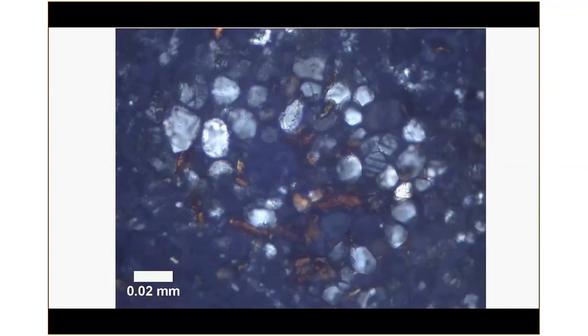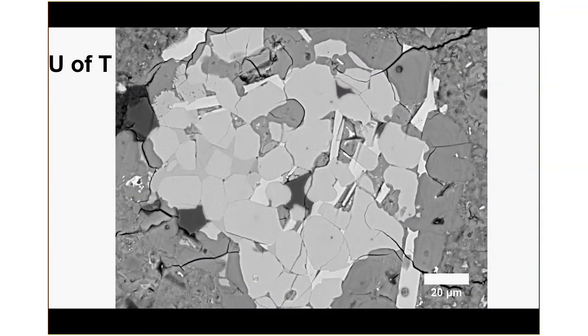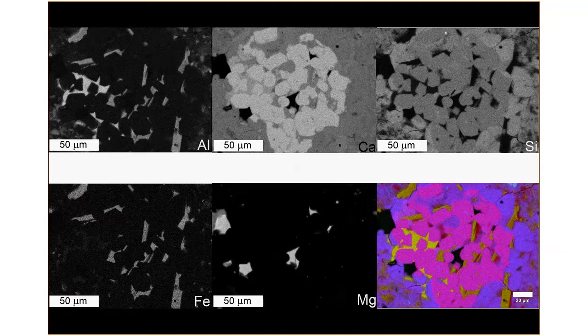Cross-polarized light, seeing the crystals and the ferrite. Again, University of Toronto, and Carl Peterson did some scanning electron microscopy, where he actually mapped all of the various elements that are in this, if you're familiar with backscattered imagery, and using these colors starting up in the upper left-hand corner. There's the aluminum, that's your calcium aluminates.